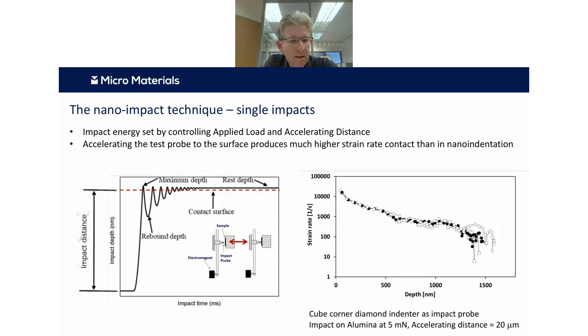So the nano impact test technique, there are two different ways we can run this test. We can run single or multiple impacts. So if I start off just talking about a single impact test, we typically have a test technique where we pull our test probe away from the surface and then we rapidly accelerate it to create this high strain rate impact, as shown schematically on the bottom left there. And then as it hits the surface, the test probe bounces and eventually comes to rest. And this happens in a small number of milliseconds.